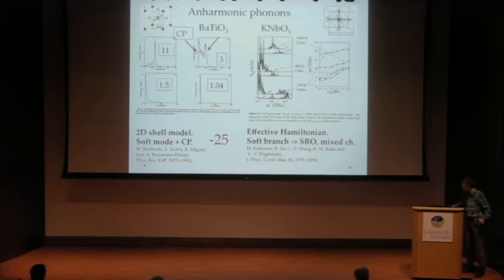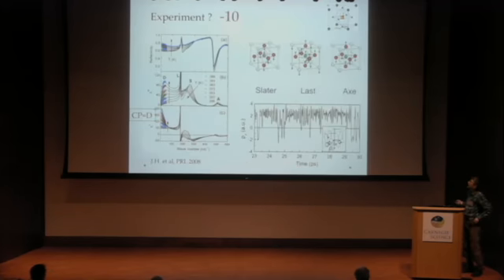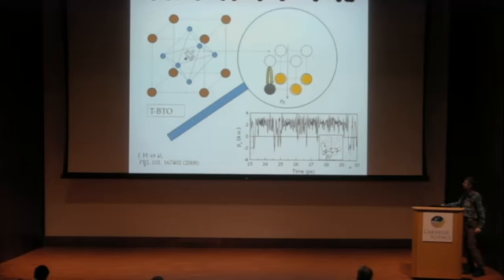And so the question is how it is in experiment. Ten years ago, it was possible to see some signature of the central peak in barium titanate, in the tetragonal phase. So in addition to the Slater mode, I mean the phonon frequency of the soft mode, there is a new excitation which corresponds to jumping between different sites. I illustrated it here in more detail. So we are in the tetragonal phase, so we can think about 8 minima around the center of the oxygen cage. 4 of them are occupied because we are in a single domain tetragonal phase.